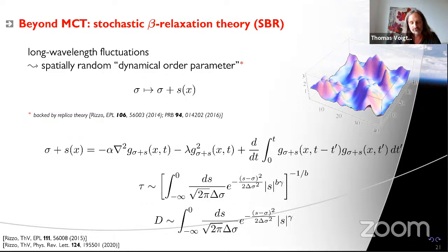It will change nature across the mode coupling transition because it will change from something that's governed by the mean distance parameter sigma to something that lives in the Gaussian tails of the distance parameter, from something that is glassy, on the liquid-like tail. And you can then derive scaling laws for how the relaxation time and the mobility or diffusivity should behave as a function of the distance parameter sigma here. And it's a bit more complicated than the usual power laws, but it's nothing that cannot be calculated.